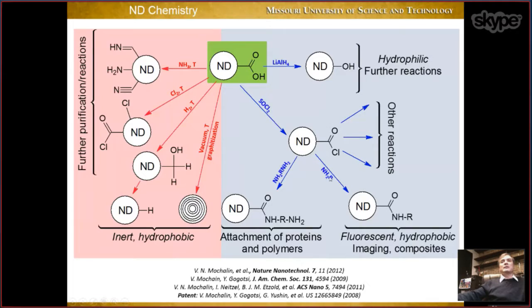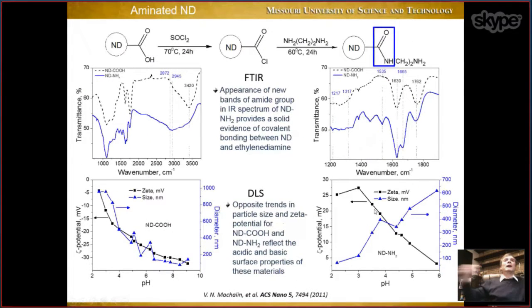And then, for example, these acyl chlorides are very reactive, and you can use them to produce many different products. In particular, we use them to attach diamines, as shown here, to produce aminated nanodiamond with amino groups on the surface, and monoamines to produce nanodiamond terminated with long hydrocarbon chains, which is R here. So again, we are not doing anything new in terms of chemistry. All those are known reactions. But at that time it was very new for nanodiamond.